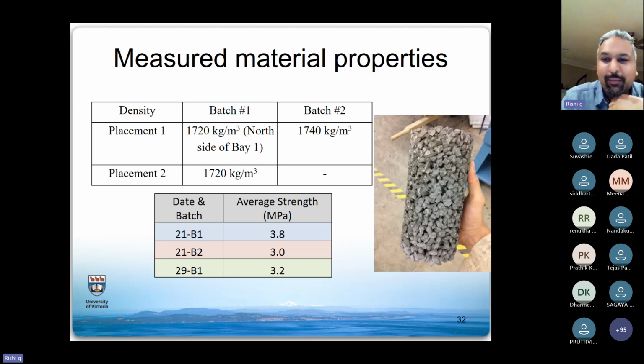Before I started, I know there was some discussion happening on concrete and durability and all of that. So just to put this out there, the cylinder that we are holding in our hand looks very nice. It looks like porous concrete. If somebody was doing regular concrete, they would say that's very bad concrete. It has lots of voids, poor compaction. But in porous concrete, that actually looks very, very nice. Good distribution of aggregates. Our density had gone down from 2,300 to about 1,700 kilos per cubic meter.